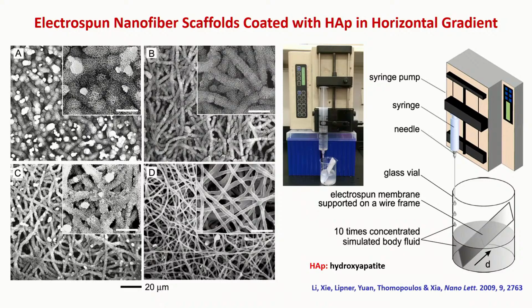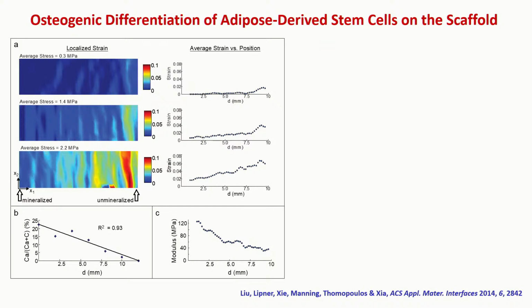So here I just show you SEM images we took from different regions of the scaffold. This is from the bottom region, the very bottom one, and then you move upward in this direction. So you can see when you move to the top, eventually you are going to have very little deposition of mineral. In this particular case, we are using electrospun nanofibers as the basic structure for the scaffold. And then onto the surface, we deposit this hydroxyapatite mineral phase in a spatial gradient. And we also tested their mechanical properties, as you can see over here.